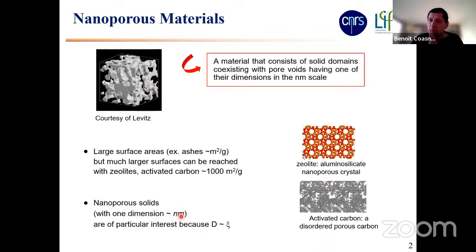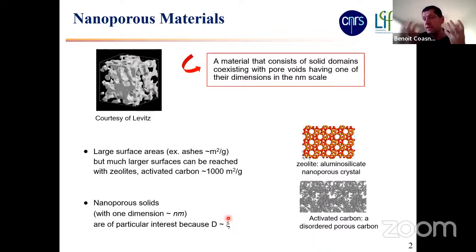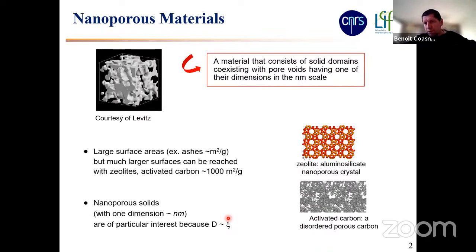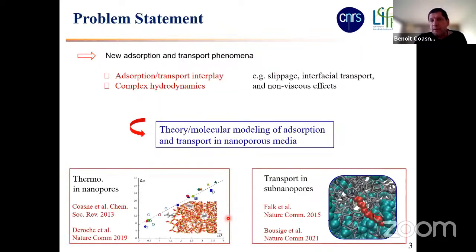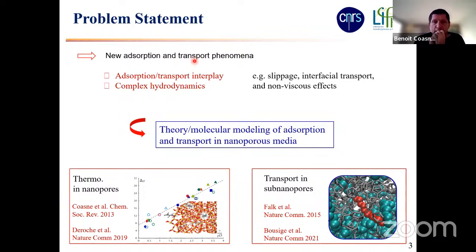This scale — the nanometer scale — is typically of the order of the range of intermolecular forces that are responsible for the cohesion of liquids. For instance, if you take liquid water, typically beyond one or two nanometers, water molecules barely interact with the other molecules. So if you confine a liquid like water inside these nano cavities, you are introducing a sort of interaction cutoff that is going to produce some new effects. Because of the large surface area and the confinement effect, there are many new adsorption and transport phenomena.